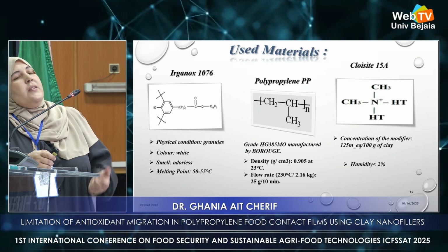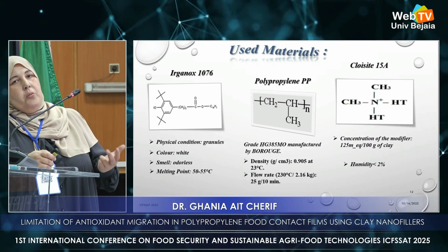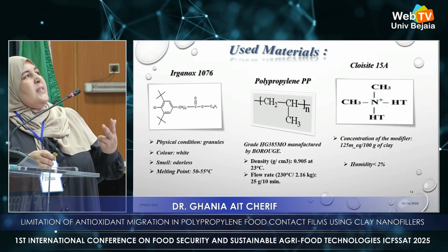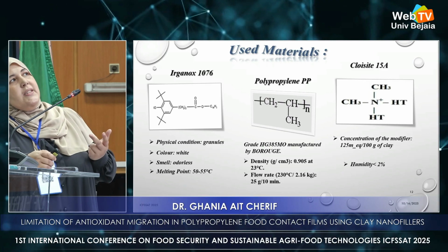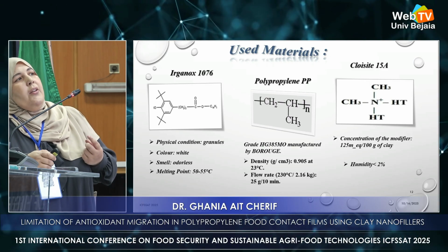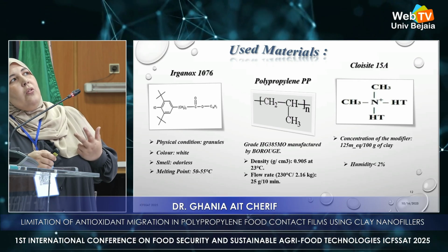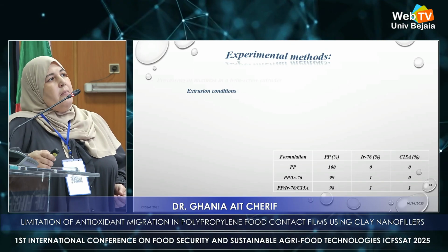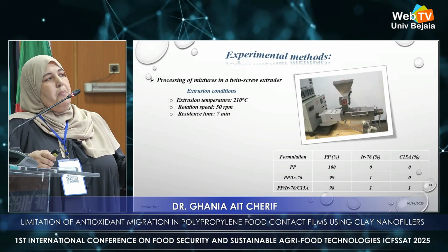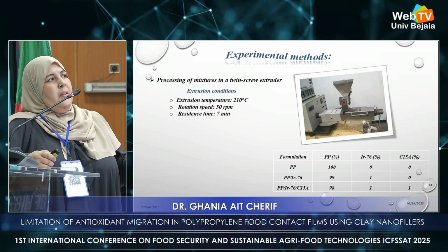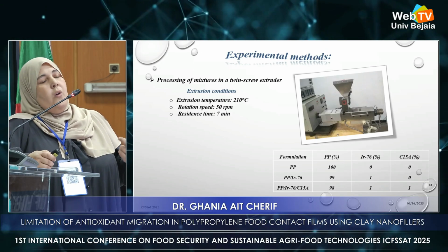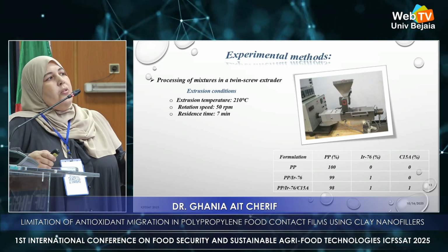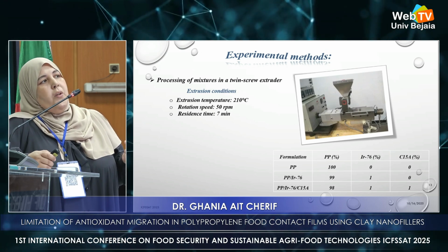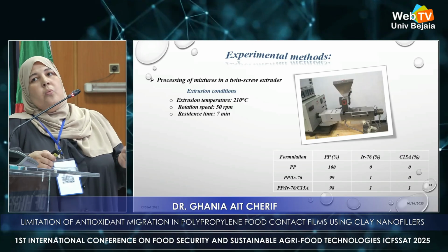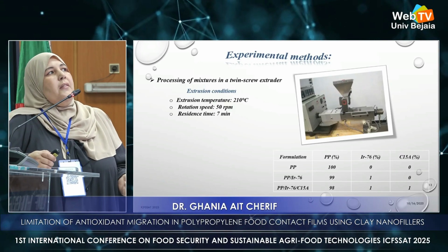For this work, we used three materials. The first one is polypropylene. The second one is a stabilizer, which is Irganox 1076. And finally, an organomodified nanofiller, which is Cloisite 15A. These tables list the different materials prepared. The first one is the neat PP. The second one is polypropylene with 1% of stabilizer. The third one is polypropylene with 1% of stabilizer and 1% by weight of nanofiller.